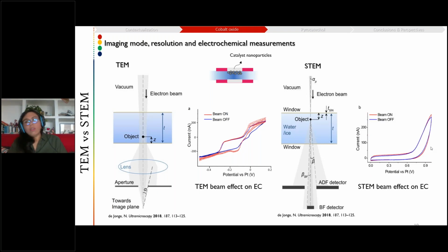So that we don't observe in STEM mode. Besides the fact that we are able to focus more on the top window, which is the one where the nanoparticles are, also the fact that we don't observe any interferences from the STEM mode on the electrochemical behavior led us to use this imaging mode.